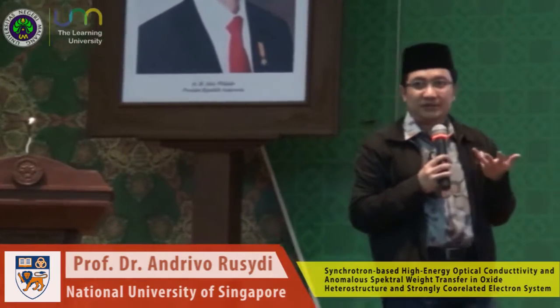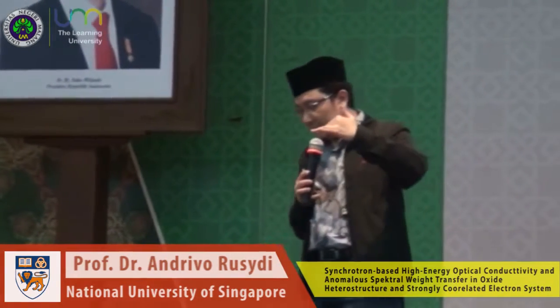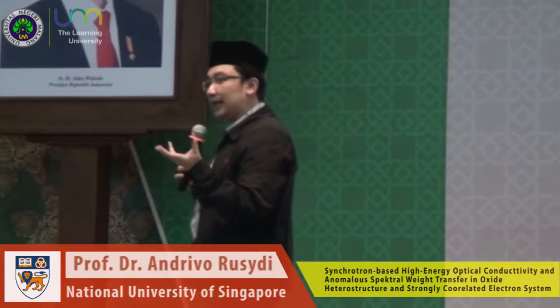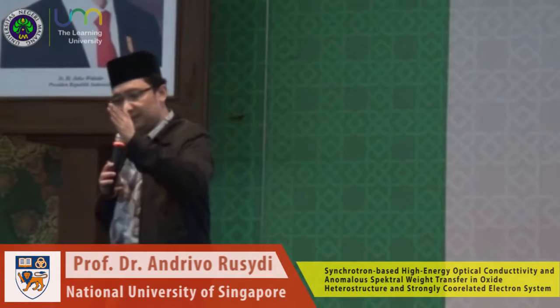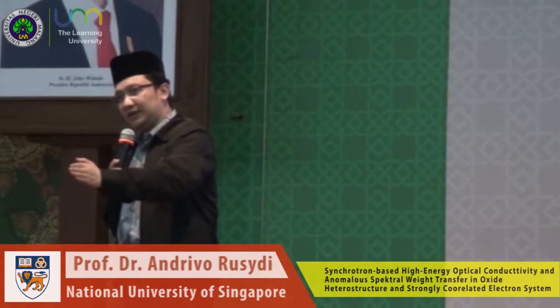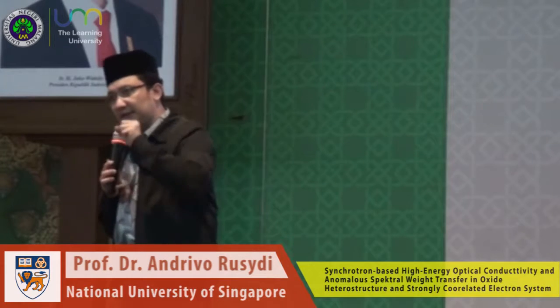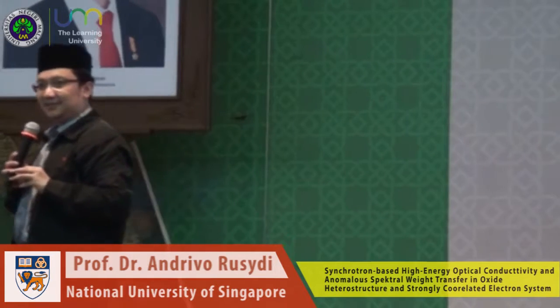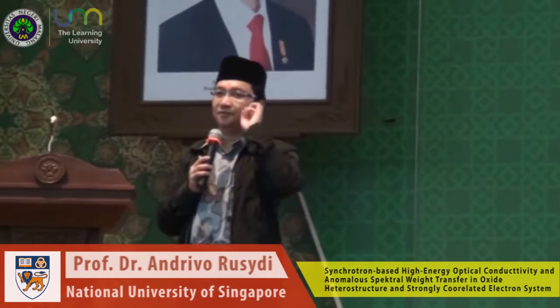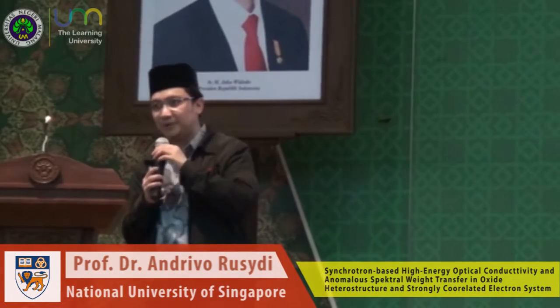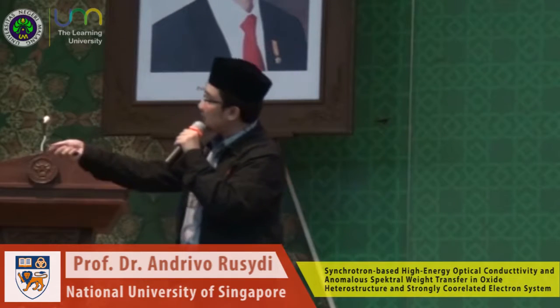Now one can make, for instance, a completely different device now, based on only a simple number of layers. I can create metal on this side and insulator on the other side by adding one layer and creating oxygen vacancies. And I can put it back, it becomes an insulator if I put the oxygen vacancies back. Put the electron back or put the oxygen back, then you can create so-called insulator-metal transitions.